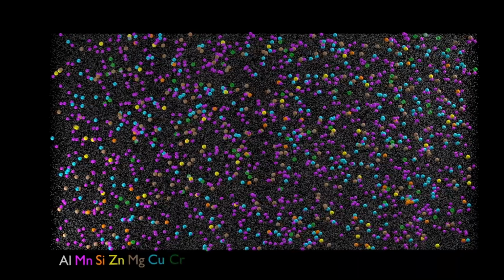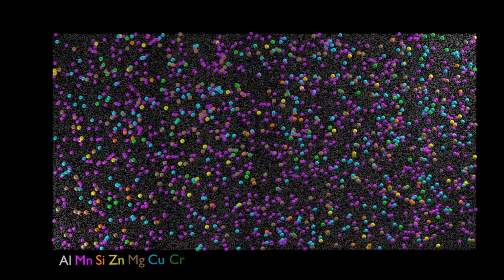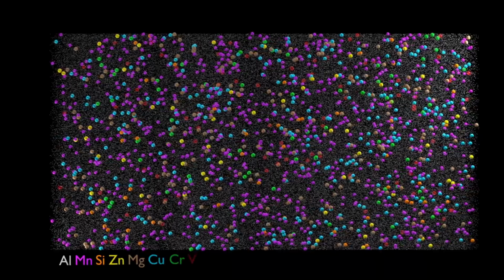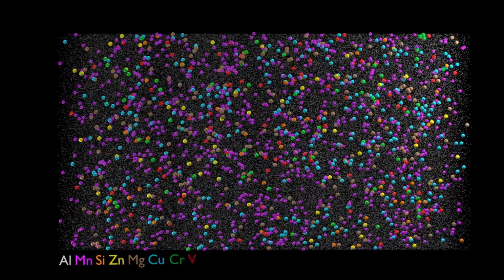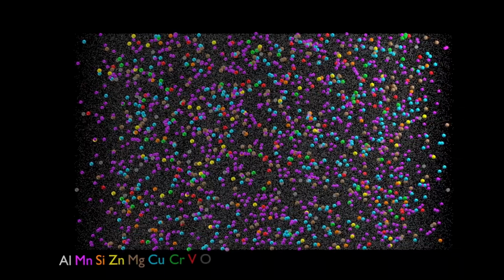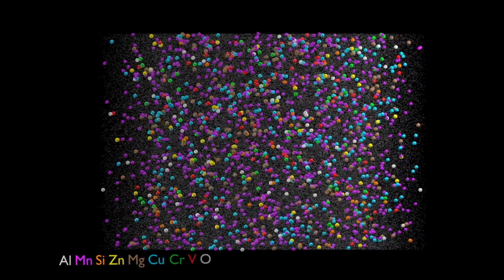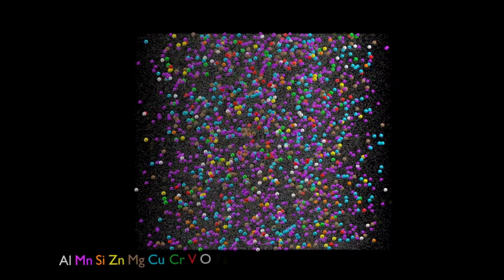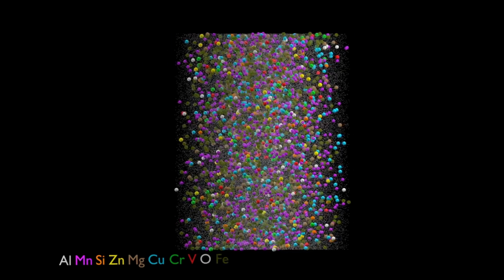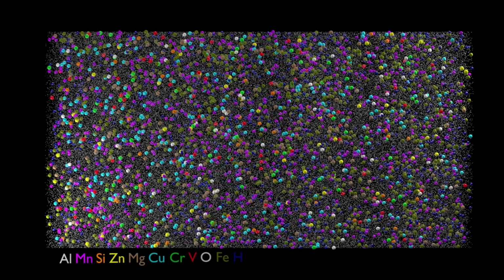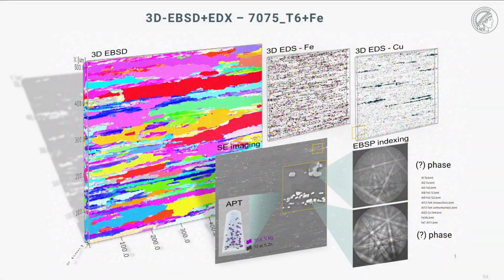That means for some high-end packaging application, this material can no longer be used, but it also shows nicely that a very interesting option for research in the field of aluminum consists in identifying alloys which are more robust against tramp elements as these accumulate over the recycling cycles. So that is, so to say, the science of less pure materials.